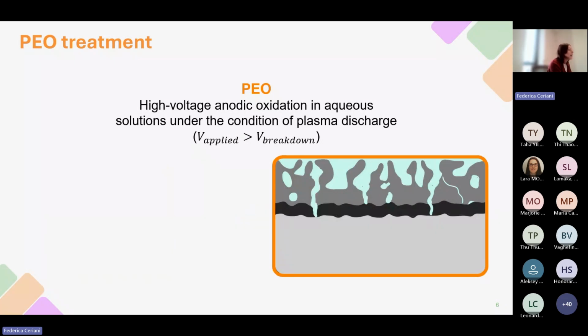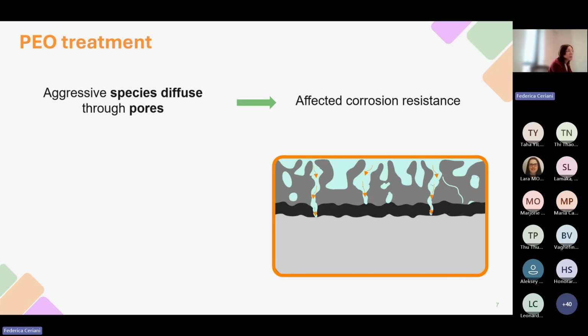Unfortunately, PEO coatings are characterized by a high level of porosity, and the formation of pores is intrinsically related to the occurrence of highly energetic discharges during the treatment itself. So it is quite difficult to completely avoid the formation of defects within a PEO layer. The presence of pores is of course detrimental in terms of corrosion resistance, since aggressive species can easily penetrate through them, reach the metallic substrate, and cause its corrosion.